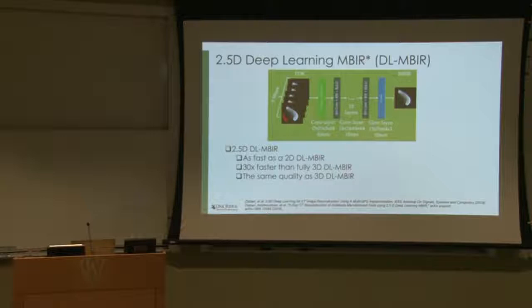Anyway, so one thing Amir has been leading is, how do you do it for 3D? How do you do it for large 2K volumes? And he's developed this network called the 2.5D deep learning network, which essentially learns by taking two 3D volumes, but not doing 3D learning. It takes just a few slices of an image from here and then has a target reconstruction. It turns out he has been showing that doing this is much faster than doing fully 3D networks, and the quality is pretty much the same. So you can look at his paper, and I've been working with him on using this for additively manufactured parts.